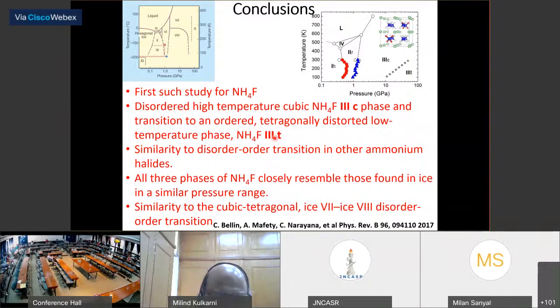So there is a strong similarity between all the ammonium halides. At room temperature, it is not having a similarity in the structure with the ammonium halides, but as you pressurize it and lower temperatures, ammonium halides actually behave similarly. And again, you can see that the three phases in ammonium fluoride exactly mimic what the ice structure has. So this is a very, very interesting behavior.